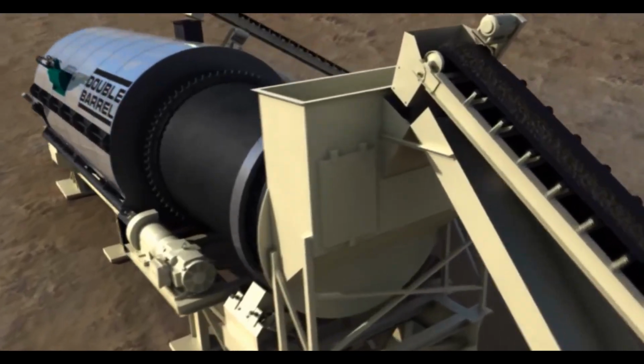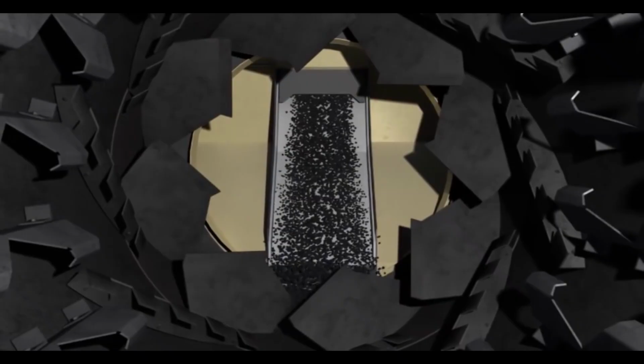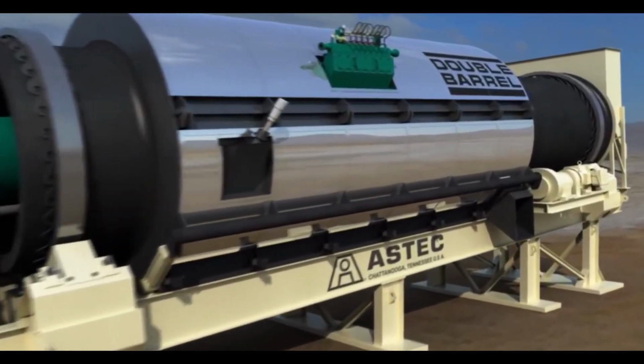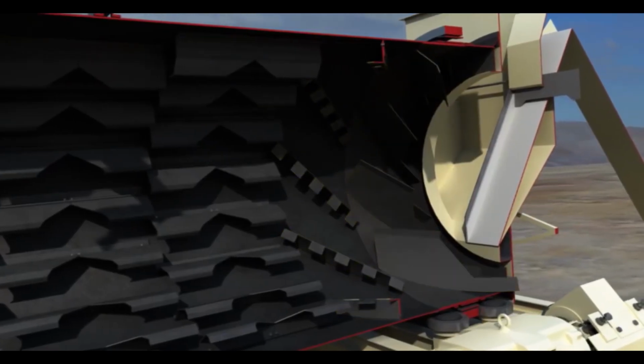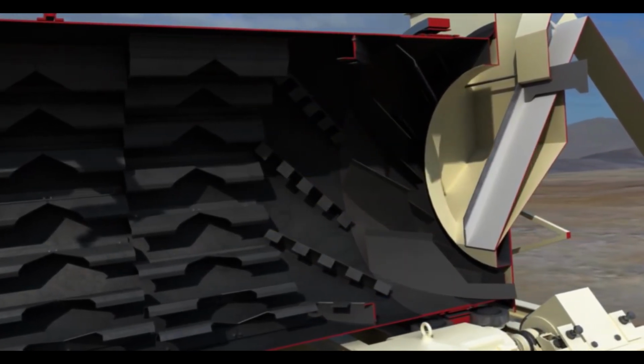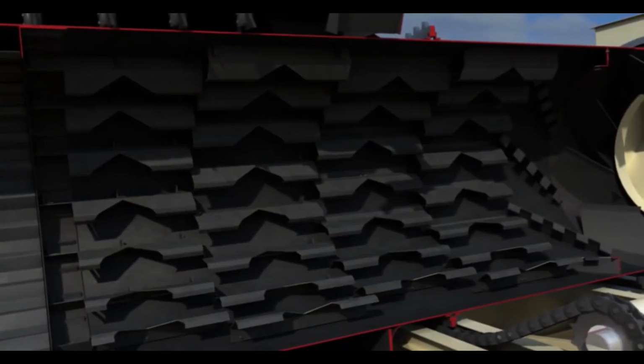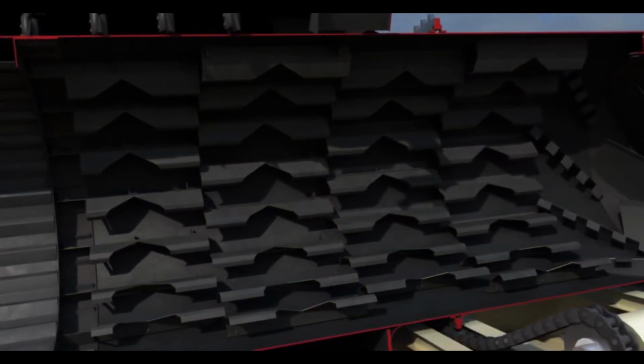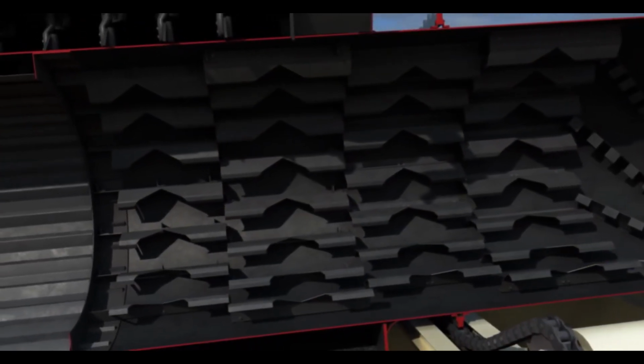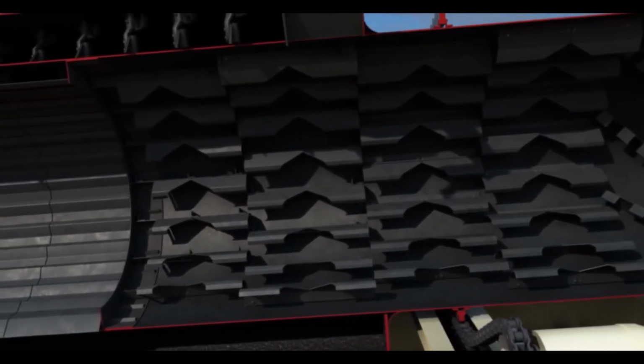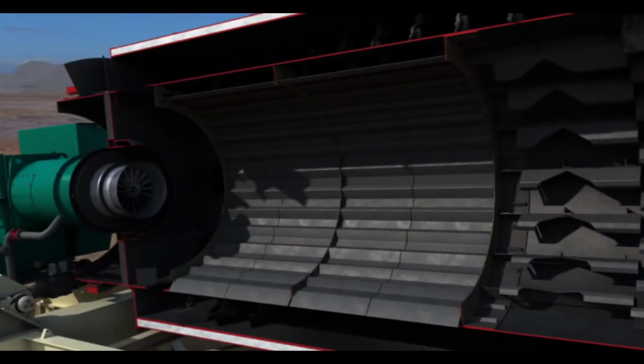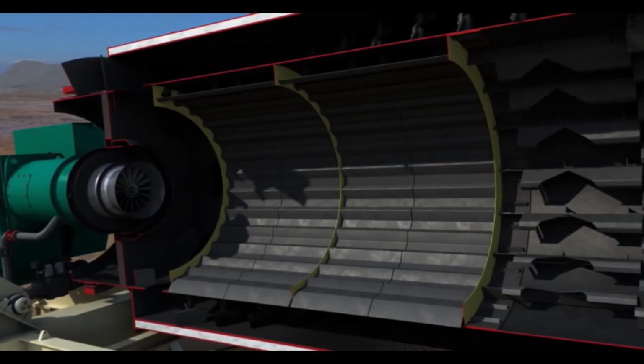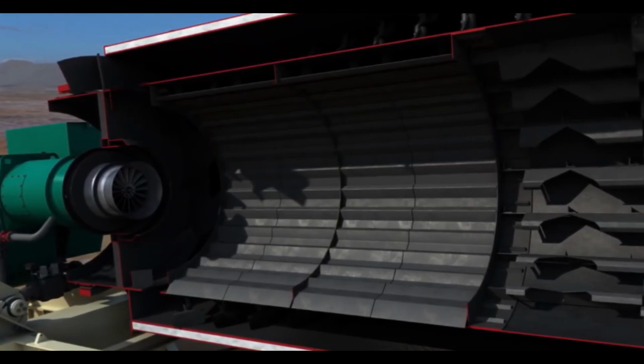Virgin aggregate in correct proportions enters the inner drum through a gravity chute outfitted with a flop gate to restrict air entry. The inner drum contains 3 zones, with flights designed for a specific function. Conditioning flights at the inlet end break up any clumps or sticky material. Showering or veiling flights lift and pour the material evenly through the hot gas stream, transferring heat to the cooler, moist aggregates. Material dams assure the showering flights are full to maximize heat transfer to the material veil.